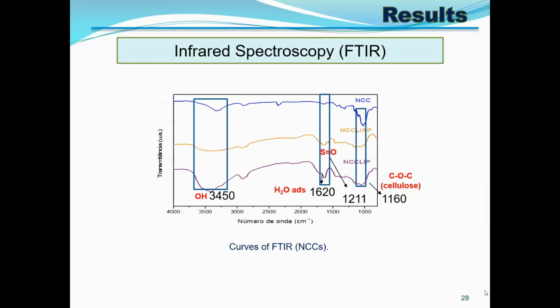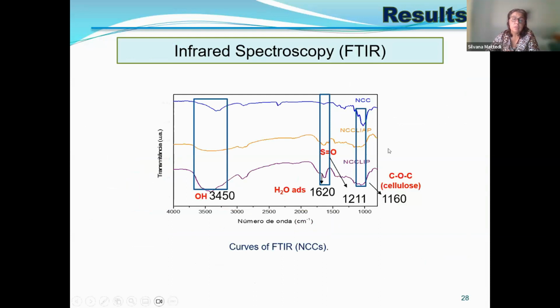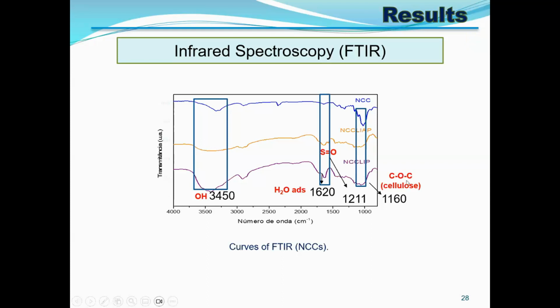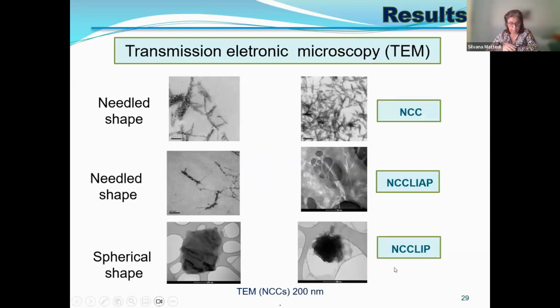imidazole. So all of them have the typical cellulose bonds and sulfuric bonds. The sulfuric bond is much more present in the ionic liquid treated material, and also a higher band of OH, hydroxyl bonds, which is much higher with the hydroxyl ionic liquid than you have for sulfuric acid or for the imidazolium material.